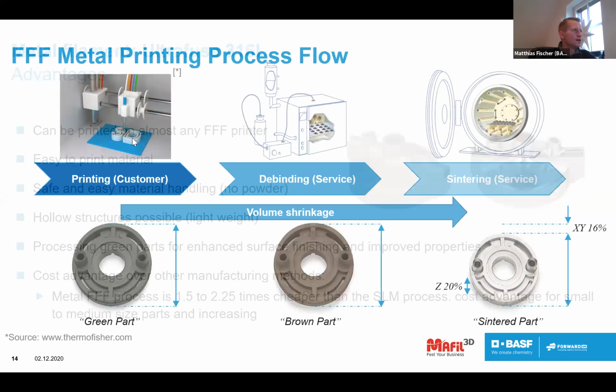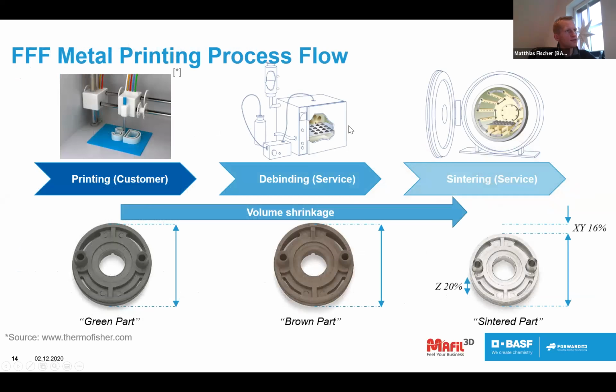In general, you need to print the part first. So we talk here about the green part, and then we have a debinding and sintering service, which is afterwards sintering the parts, or first of all debinding the parts, which means reducing the polymer matrix of the part. It will shrink. It's about 20% in the Z direction, and in XY about 16%. So you need to consider this already when you print the parts. You need to print them usually bigger, but therefore we have really good processing guidelines. And afterwards it will be sintered. Also, it's the same service provider.